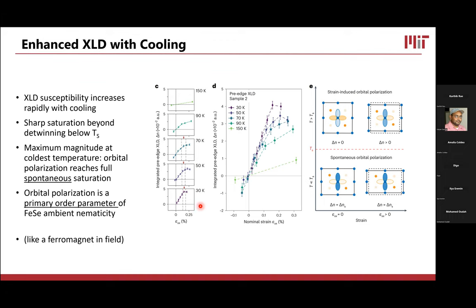The XLD is saturated, which means the orbital polarization is saturated. So if we put all of this data together, it looks like this, where you have this increasing susceptibility as you get colder and then a saturation at low temperature. So if you're looking at this and you're thinking this looks just like the magnetization of a ferromagnet in a magnetic field, then I would agree with you.